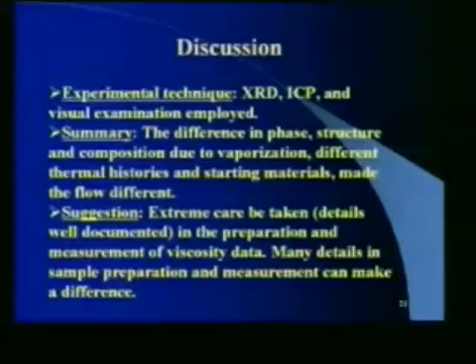So we wanted to compare these two systems, and it became a question of why they were different. Well, materials scientists like things like X-ray diffraction, inductively coupled plasma analysis, and so on. So we used a variety of techniques to see if there were differences in phase, structure, and composition. And it turns out there are, because of the way these things are formed, the thermal histories and starting materials, which really led to the question that you have to be very careful when you're making this material to make sure that it has the right properties that you want. And I'll show you a few examples of that.